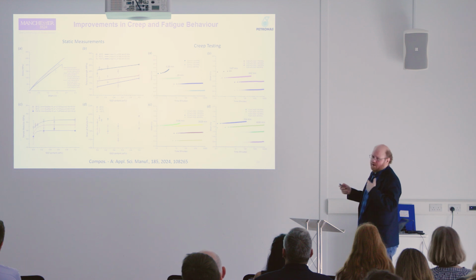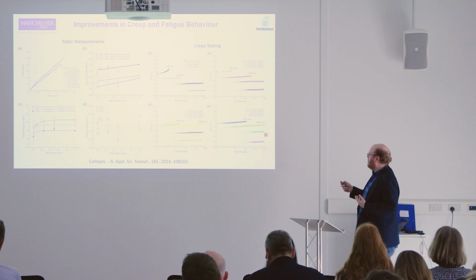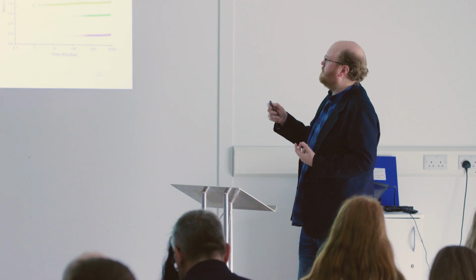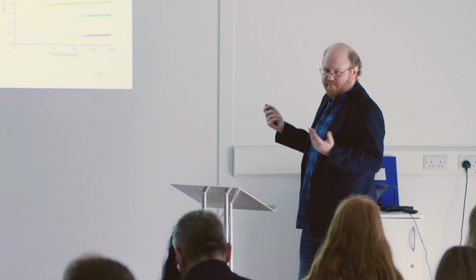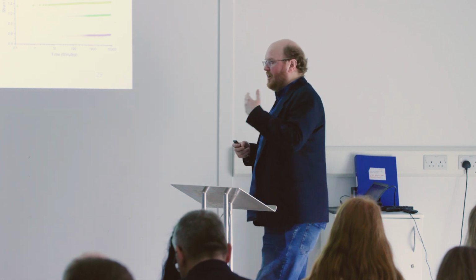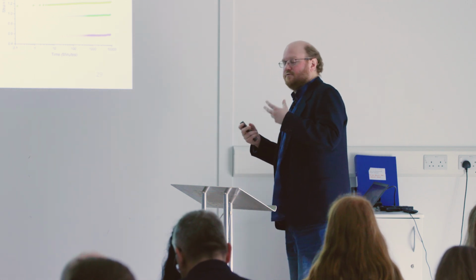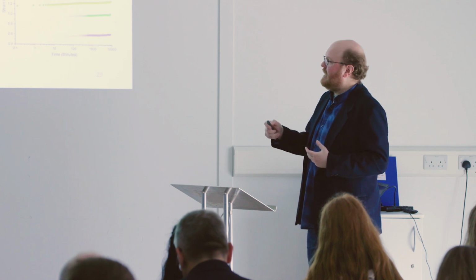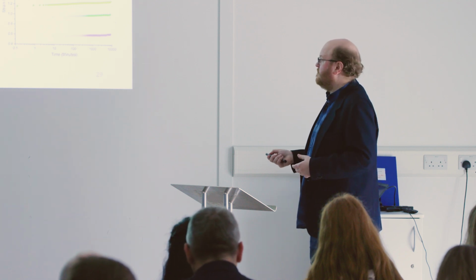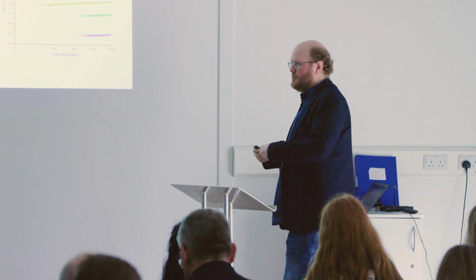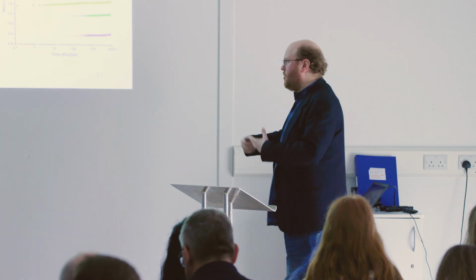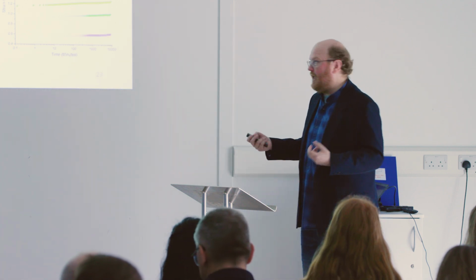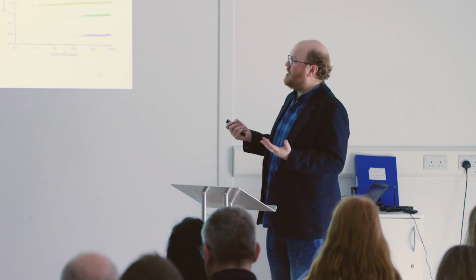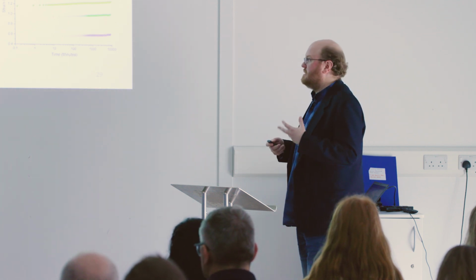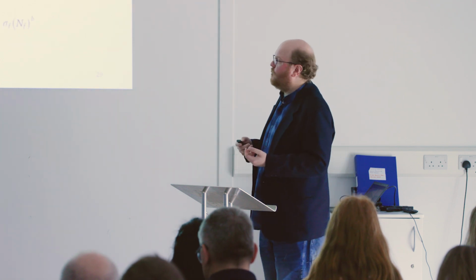So of course, at more realistic operating loads, these ones here are going tens of thousands of minutes, basically longer than we were allowed to use the machine for, whereas these ones here are failing at 29 minutes, and this one here, 4,700 minutes. So that creep, where you've got a continuous load, even if the benefit in a static measurement might only be modest, is what's important for industry. If your composite is under load, say it's in an airplane wing, you want it to last the whole flight, not just takeoff. And so understanding those properties at those longer lifetimes is very important.